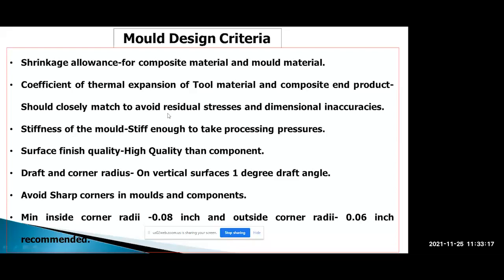And during curing also, a lot of residual stresses will be generated. The mold should be stiff enough to take the processing pressures. Like in the autoclave, where we are applying pressure, it has to take those pressures.